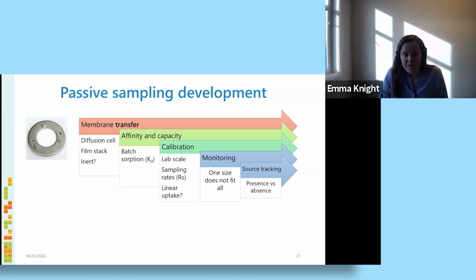So this is the receiving phase or the sorbent phase, and we usually do a batch equilibrium experiment to get a KD value or a KS value. And then we can calibrate this in the lab. So we can do a time series of samplers that can be taken out at days 1, 2, 7, 14, and 28, let's say. And from there, we can get an idea of the uptake rate or our sampling rates, RS. And from there, we can do some monitoring.